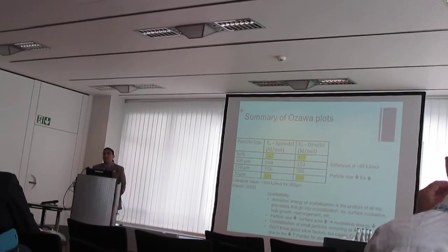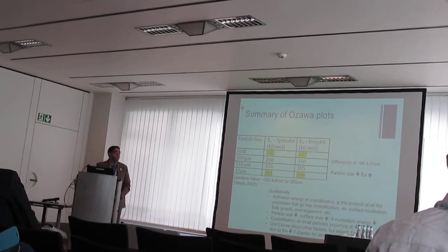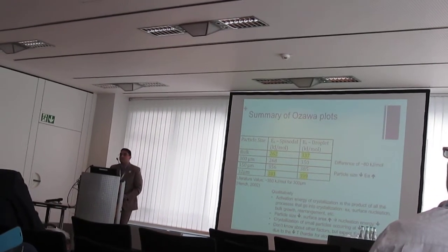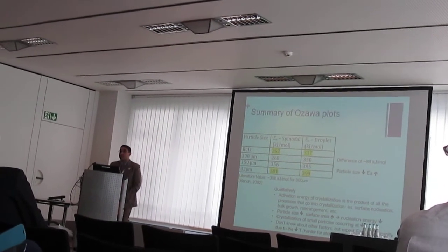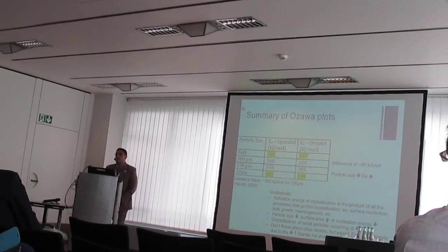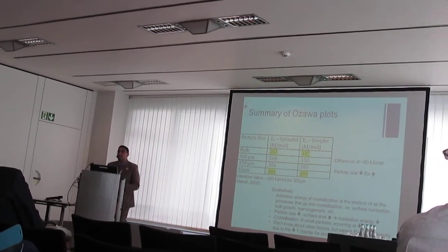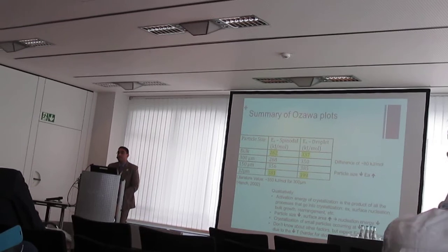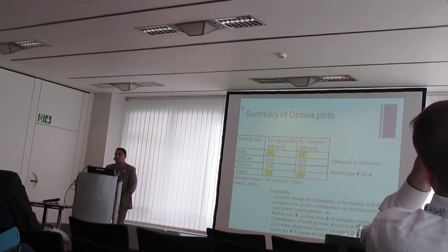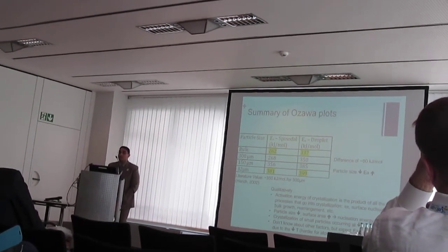But because the temperature of crystallization is lower for the smaller particle size, we think that that is what causes the activation energy - the rearrangement takes more energy to occur. And this is of course also a hypothesis.